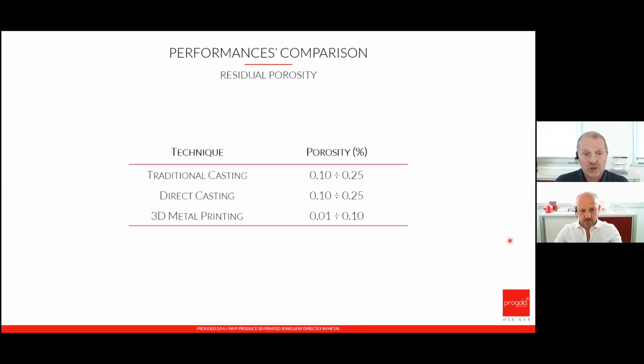In all previous research works that we did, we have always paid particular attention to this matter, that is the incidence of residual porosity. Without reporting a lot of data here, we can decidedly affirm that residual porosity is lower, even 50–60% lower, with the SLM compared to casting. And in fact, here there are some software results checking the porosity quantity on the surfaces, as I showed you before.